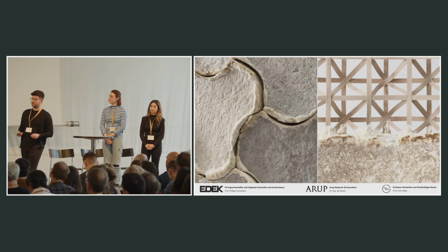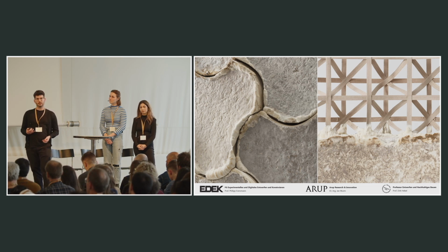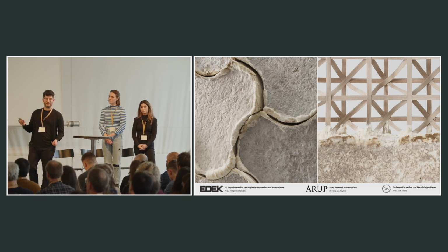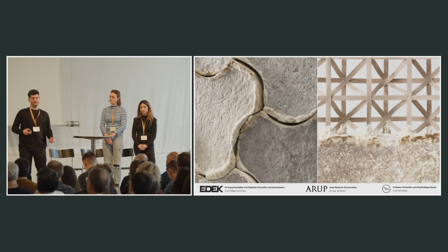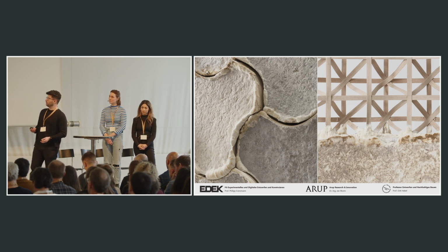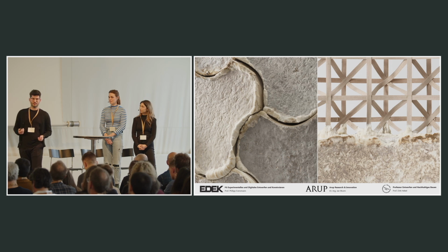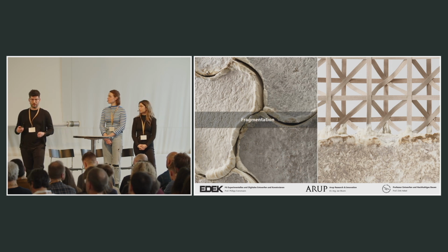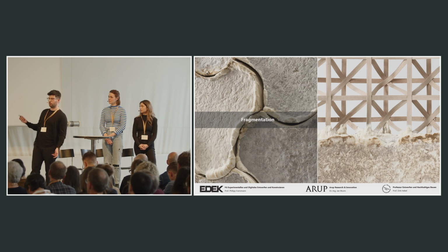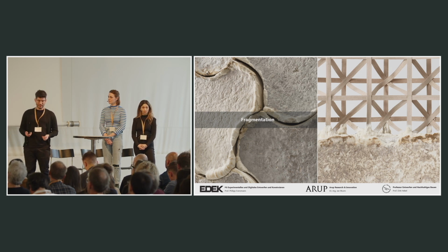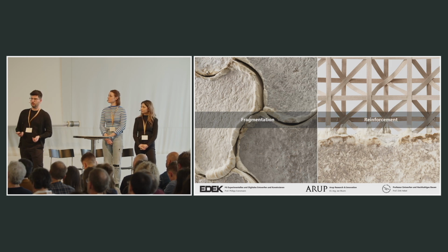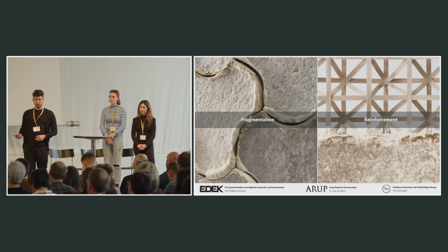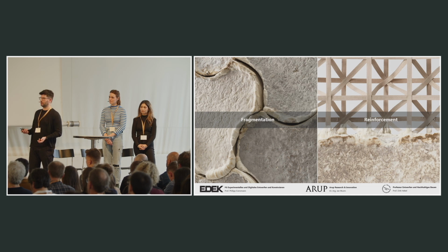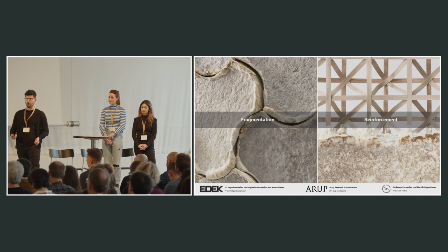What is the challenge? The challenge is that at the current stage, mycelium-based composites are unable to reach the structural dimensions that we need for panels for partition walls. It's very hard to make a 3-meter mycelium panel because it has relatively low tension and bending resistance. For this reason, we propose two strategies to address this. The first strategy deals with fragmentation, the process of reducing a larger wall element into smaller parts while maintaining structural integrity through kinematic interlocking. The second one translates a logic that we all know very well from reinforced concrete: we worked on adding a tension reinforcement made of wound veneer inside the mycelium composites in order to allow much larger spans.